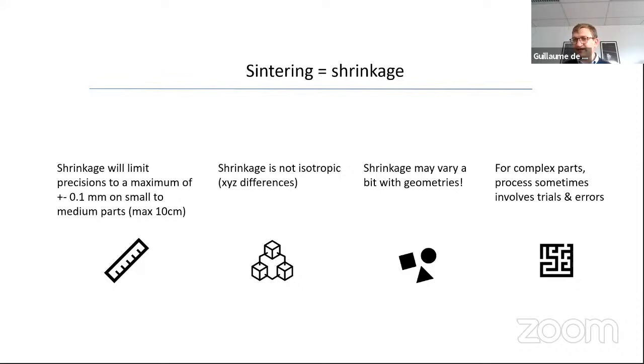And that, of course, is a problem because you would ideally want to have exactly the tolerances you were aiming for on the first shot. And sometimes it's not possible. If you are really printing something complex, and complex may not be what you think about. Complex may be not the shape itself, but varying thicknesses or the size of the part may make it difficult to have a good part on the first shot. If you need tight tolerances, you may need some trial and error before you actually get the right part. And of course, that is a drawback of the technology. All of this depends on your tolerances. Are you on very tight tolerances or not? But depending on that, sometimes you will need trial and error.